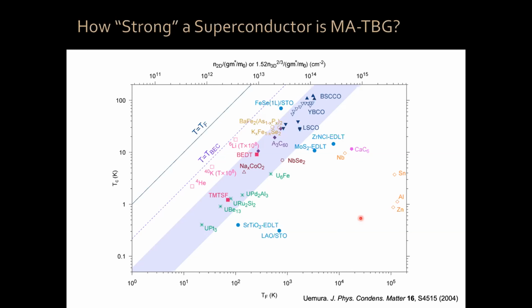Now, in this Uemura plot, BCS weak coupling superconductors, standard BCS superconductors, are in this corner. For example, take aluminum. Aluminum has a TC of 1 Kelvin, but a Fermi temperature of over 100,000 Kelvin. Aluminum has a gigantic amount of electrons that can contribute to superconductivity. Given how many electrons aluminum has available, its TC is very, very modest. This is the weak coupling regime.